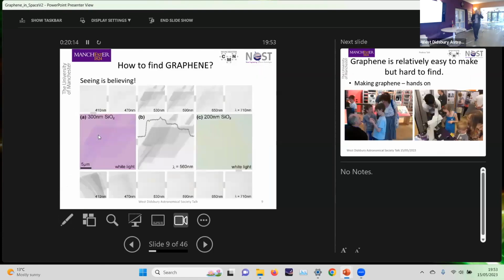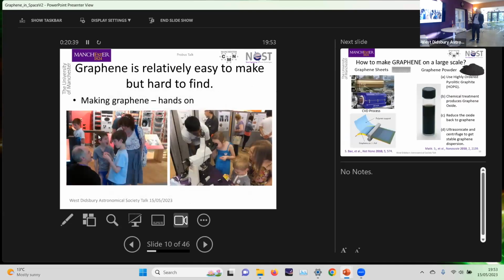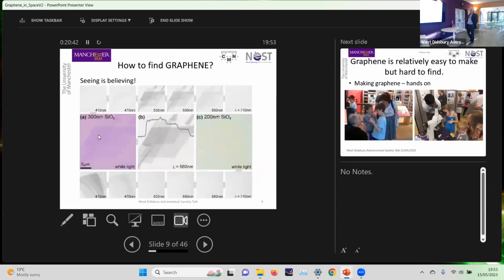Yeah. So back to this silicon and the importance of it. Kostya came over to the clean rooms and said, you know, have you got any silicon wafers? And I said yes, and gave him some silicon wafers, and he went away with them. And he started putting this stuff on the silicon wafers, and he could see these materials. And it just so happened that the sort of material we had happened to have 300 nanometers of oxide on the surface. So quite a very thin layer of oxide on the surface. But it turned out that was just about the right thickness to see the layers.